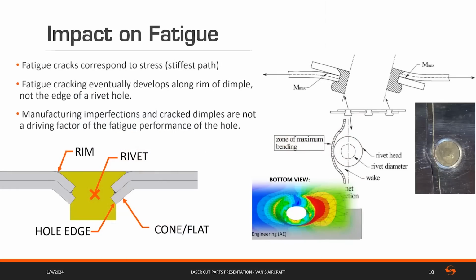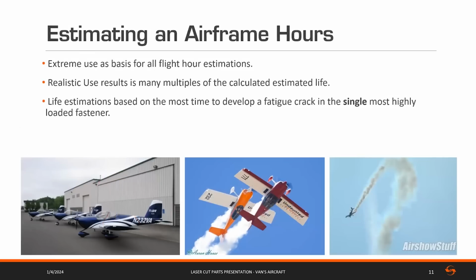And looking at that stress field in a different way, this is the predominant way in which you would see cracks happen in RVs. Historically, if you look at our service bulletins, et cetera, the stresses are higher at the rim of the dimple, just due to the way the skin transfers those stresses into the dimple. And they're the dominant driving factor in determining where that fatigue crack will occur. Realistic loading and fleet experience shows us that that's where the crack will occur. And our previous fatigue testing in years past has also shown that to be true. It's good to note here that the skins were never laser cut, and that's where we expect these cracks to form in RVs. And we get into more detail in this in the longer presentation.